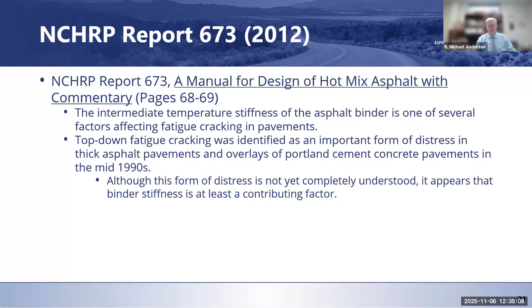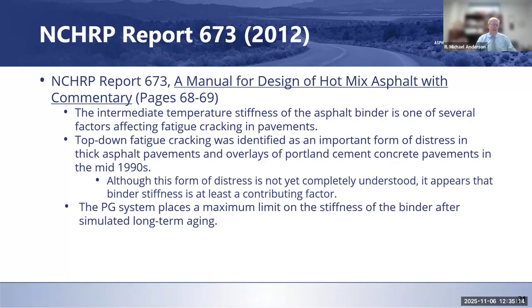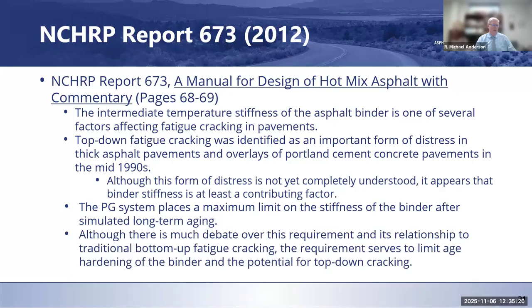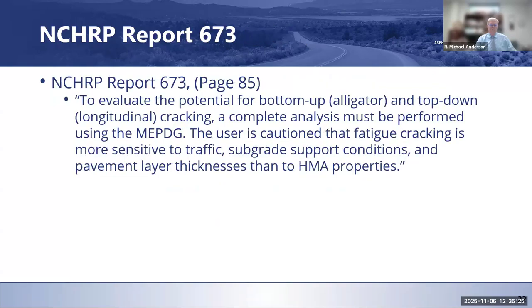It was not a distress that was completely understood, but binder stiffness was at least a contributing factor, and that the PG system places that maximum limit on stiffness after simulated long-term aging. It does serve to limit age hardening of the binder and potential for long-term top-down cracking. But they also caution that if you really were going to look at bottom-up alligator cracking and top-down cracking and longitudinal cracking, you should take a look at a complete analysis using the MEPDG, and noted that it's more sensitive to traffic, subgrade support conditions, pavement layer thicknesses, possibly than even to the HMA properties.